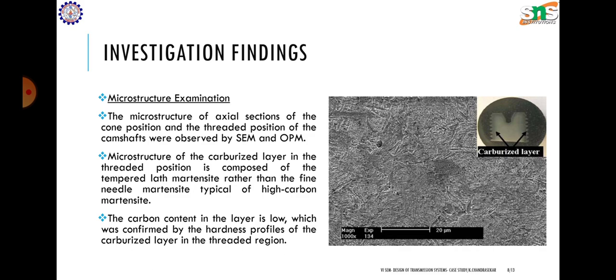Then the carbon content in the layer is low, which was confirmed by the hardness profiles of the carburized layer in the threaded region. So it is also found that the carbon content is low by means of the hardness profile in the threaded region.